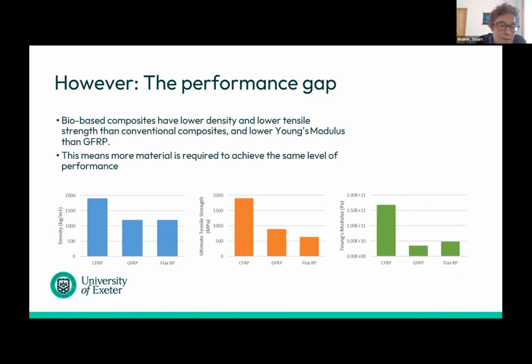So you can see here, this is for a flax reinforced polymer compared to carbon fiber and glass fiber, so CFRP and GFRP respectively. You can see the carbon fiber is basically a lot stronger than either of them. The glass fiber and the flax are not dissimilar really. So it's not a terrible performing material, the flax reinforced polymer, but it does mean that we're likely to need